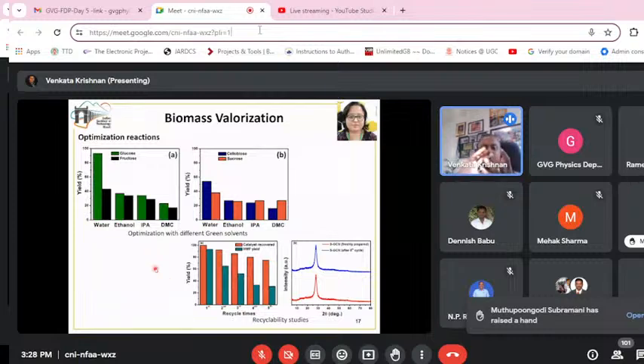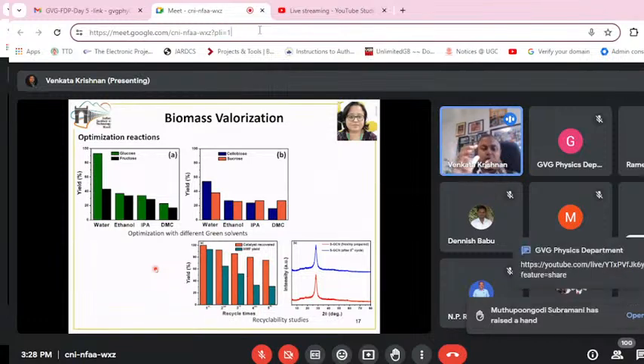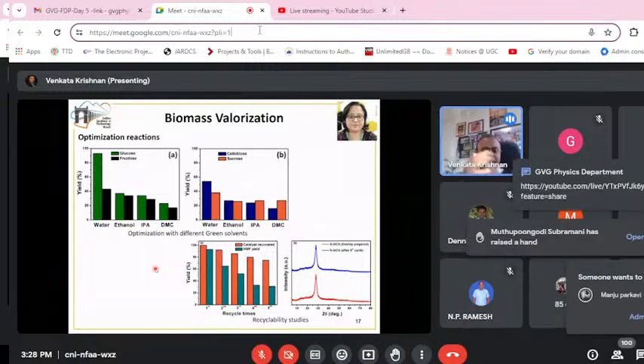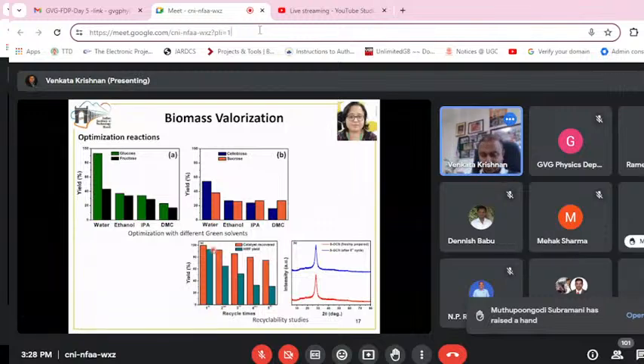This is because HMF is prone to polymerization, and once it polymerizes, it forms something called humins, which are insoluble products. These humins stick onto the catalyst surface and block the active sites, reducing the yield of HMF over different cycles.